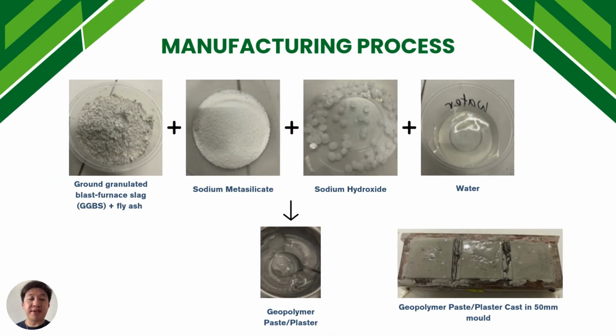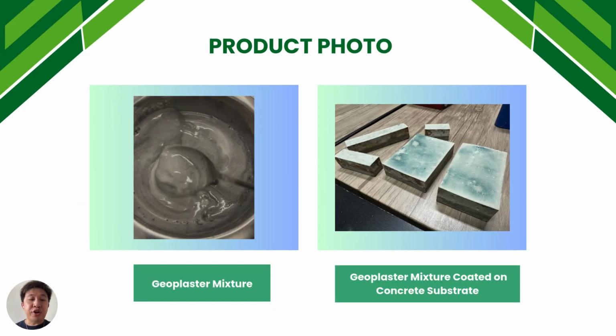This is the manufacturing process. We use GGBS with fly ash, added with sodium metasilicate, sodium hydroxide in solid form, and we add water, just water, and it becomes the geopolymer plaster. The geopolymer plaster is cast in 50 mm moulds to carry out the testing. This is the GeoPlaster mixture and the geopolymer mixture coated on the concrete surface.